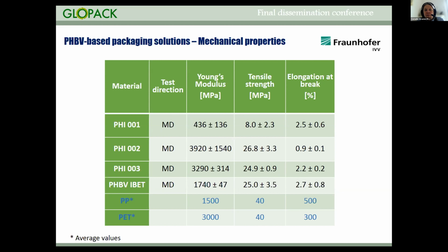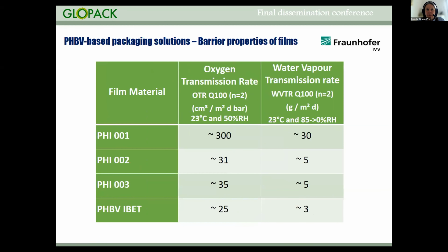Regarding the potential applicability of the PHBV material as packaging material, the weak point is the brittleness, which is leading to very low values for the elongation at break. Improvements are necessary, as mentioned already before, in some concepts we want to improve. On the next slide, you see the barrier properties of the films we measured, standardized to 100 micrometers thickness.